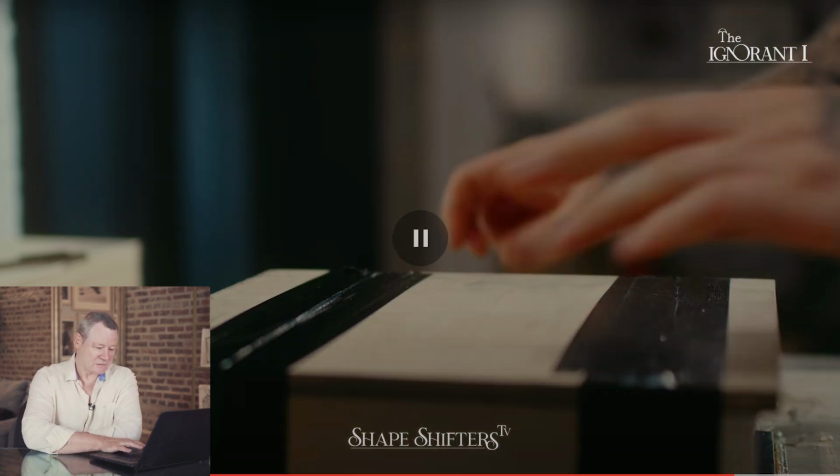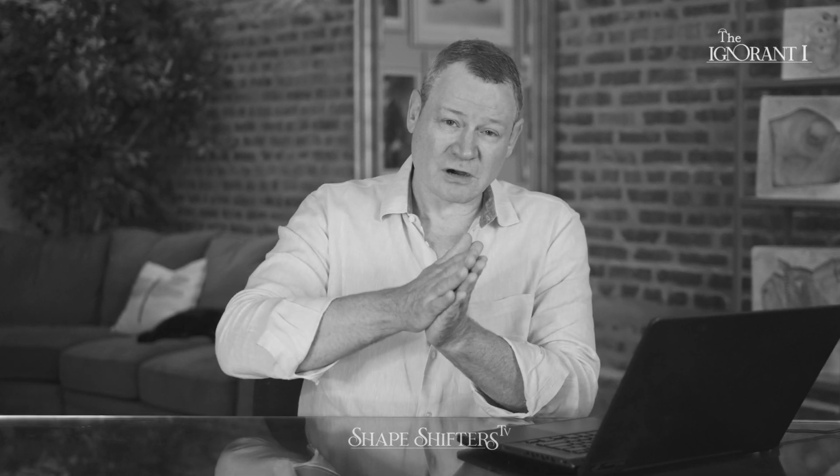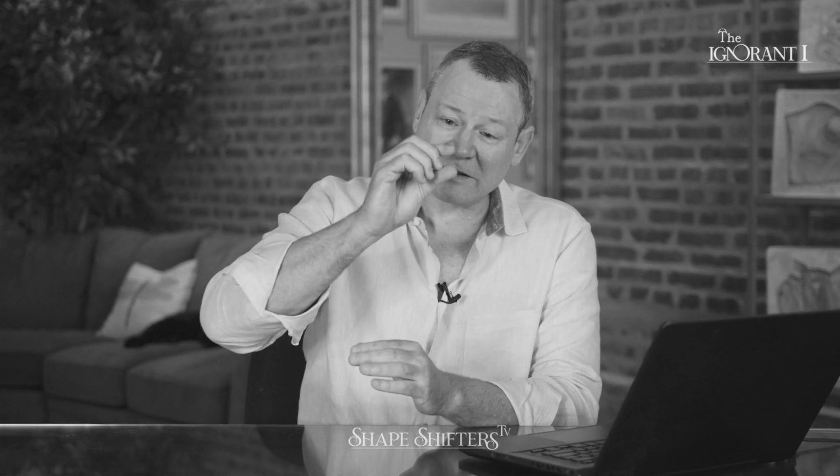Okay, so you've heard me say all these beautiful things about this guy's work here. Absolutely above stars. But he has a two-piece silicone mold. Depending on the durometer of that silicone mold, meaning the hardness of it, when he's just put it together like that and he taped it, he can actually compress the mold together, and it's going to make the negative space inside thinner or possibly irregular. And remember, he has this precision thin board in there, which is now the negative space. So he could have just closed it off accidentally. My guess is he didn't. He's done this a lot, but I saw that come down.